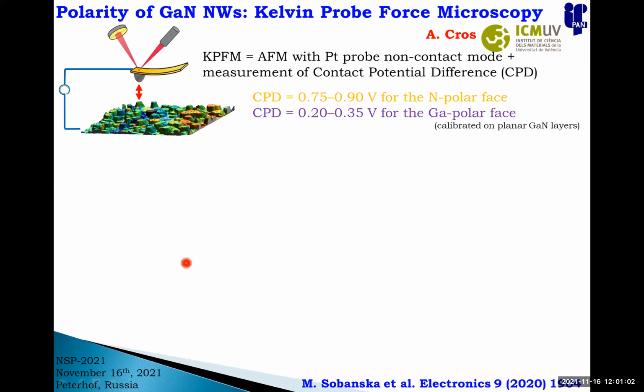So I will continue with the growth of nanowires on silicon substrate. And as I mentioned, an important parameter of gallium nitride itself is polarity, because it determines the direction of the electrical field inside, and this is important for electronic properties of these wires. And I'm going to show you that the interface, this interlayer that sits between nanowires and the substrate itself, determines not only growth kinetics, but also properties of wires, in particular, uniformity of polarity inside such an ensemble.